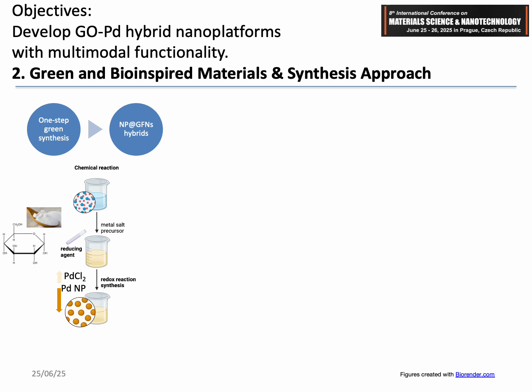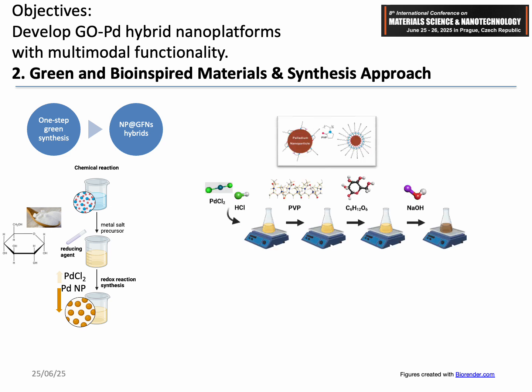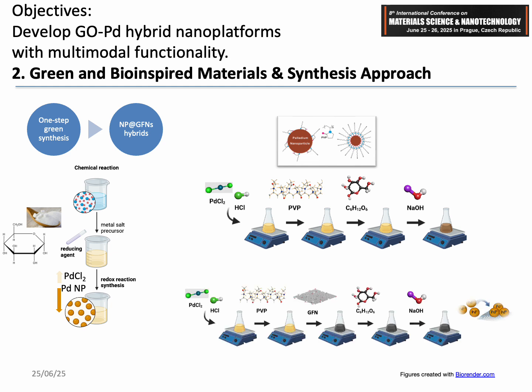Following a green and bio-inspired approach, we synthesize the palladium nanoparticles using glucose as the sole reducing agent. In a typical synthesis, the aqueous solution of the palladium precursor is added with polyvinyl pyrrolidone and glucose, then mixed together. When the pH is adjusted by the addition of sodium hydroxide, the change of color is indicative of the formation of the colloidal nanoparticles. The same reaction, just with the introduction of the graphene family nanomaterial, is done to prepare the hybrids.